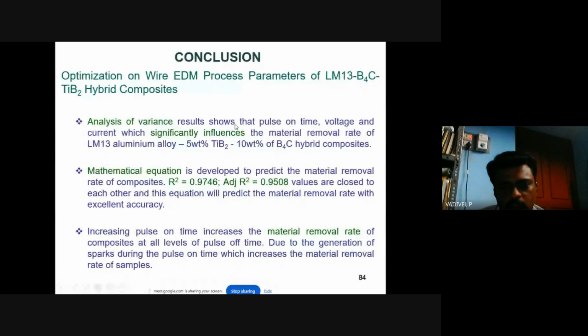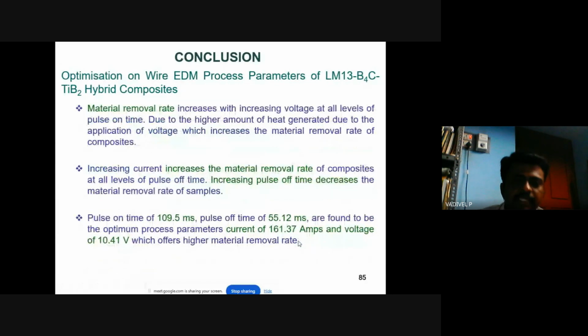The ANOVA result shows that pulse on time, voltage, and current significantly influence the metal removal rate. The mathematical equation developed for the prediction of the metal removal rate has R square and adjusted R square very close to each other, and this equation will give the MRR with excellent accuracy. Increasing the pulse on time increases the MRR due to the generation of spark between the material and the electrode. The material removal rate is increased at all levels due to the higher amount of heat generated by the application of voltage. Increasing current increases the MRR of the material, and increasing the pulse off time decreases the metal removal rate of the samples.